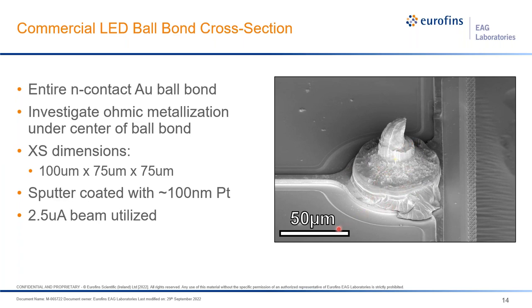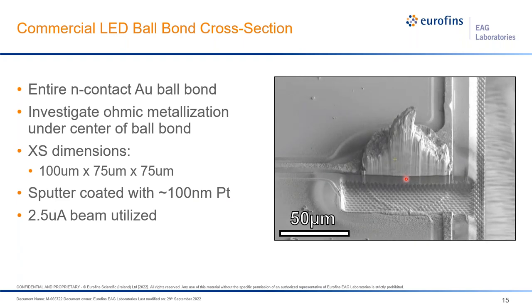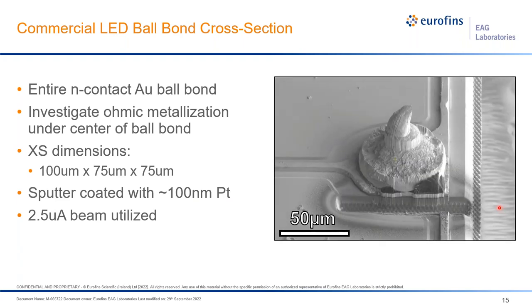In this case, we're going to make a cross section that's approximately 100 microns by 75 microns tall by 75 microns wide. In this sample, the only protection we put on it is 100 nanometers of sputtered platinum for conductivity sakes. We're going to utilize the majority of the ball bond material as the etch stop for the analysis. And when we play this little film here, you can also take note of the damage that's happening to the sample around the outside. In this case, we're using a 2.5 microamp beam to make the cross section. And so here's a little video showing this process.